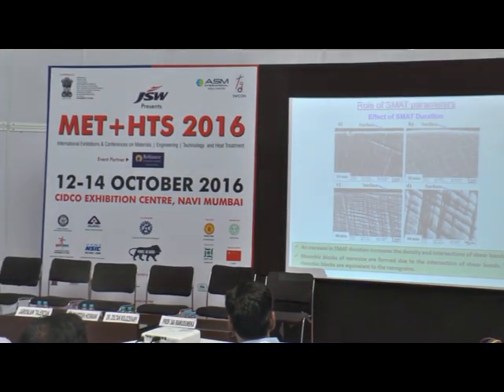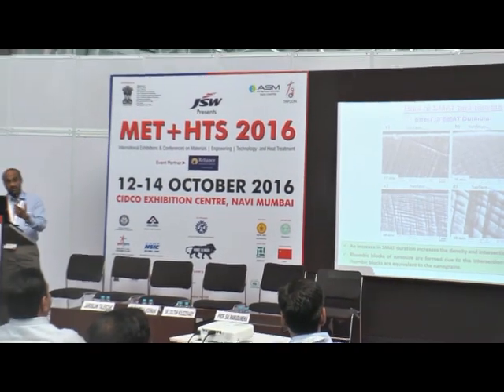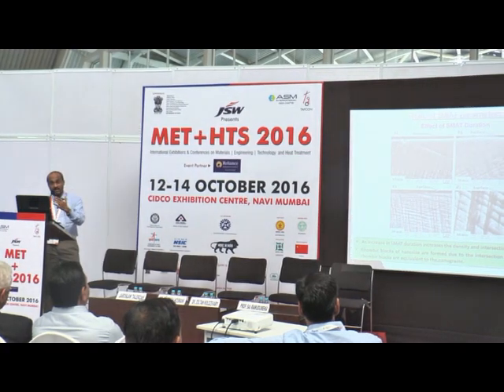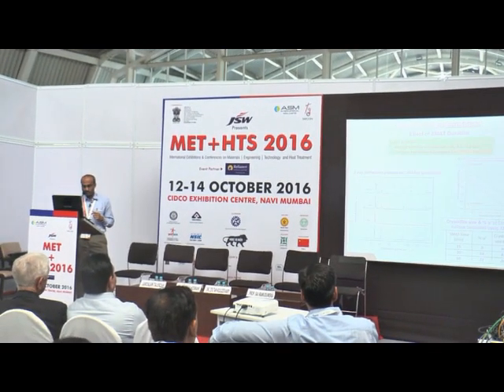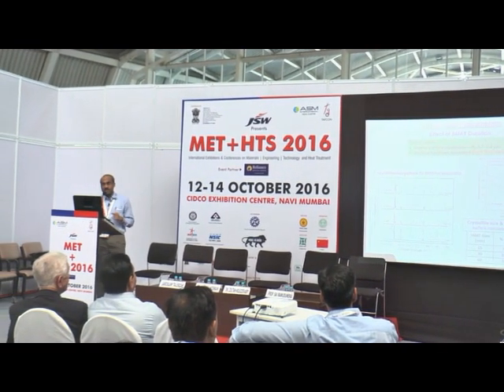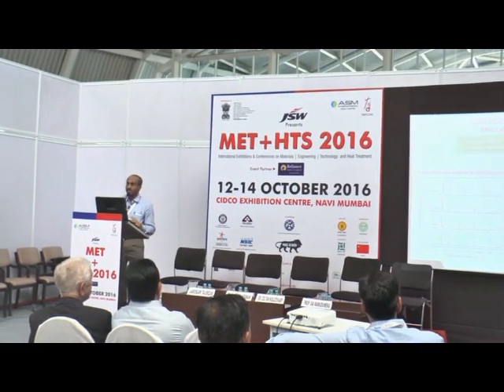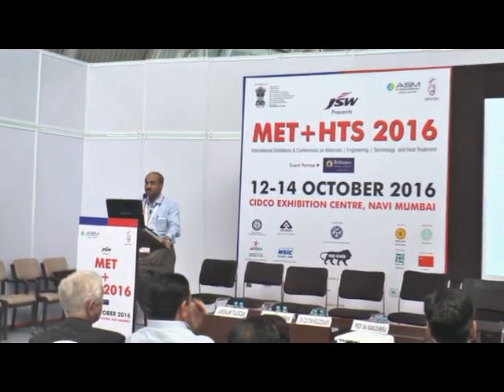So these rhombic blocks play an important role in the oxidation behavior of the material, that is the passivation ability and the nitriding process. At the same time, since it is an austenitic stainless steel, you know that there is deformation induced transformation, called deformation induced martensitic transformation. Since the process is plastic deformation, there is formation of martensite at the specimen surface. And this martensite quantity is very much dependent on the SMAT parameters. As you increase the SMAT duration, the percentage of martensite will increase.